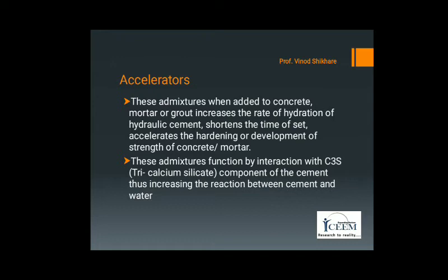Accelerators such as triethanolamine are comparatively expensive. Recent studies have shown that calcium chloride is harmful for reinforced concrete and pre-stressed concrete. It may be used for plain cement concrete in comparatively high dose. The limits of chloride content in concrete are given in durability of concrete.